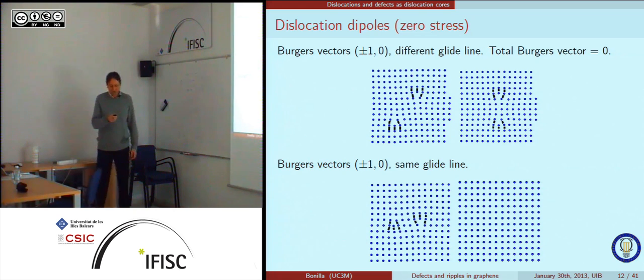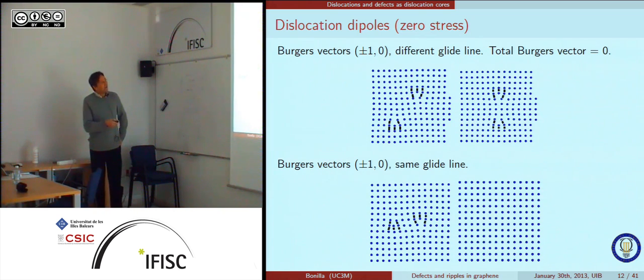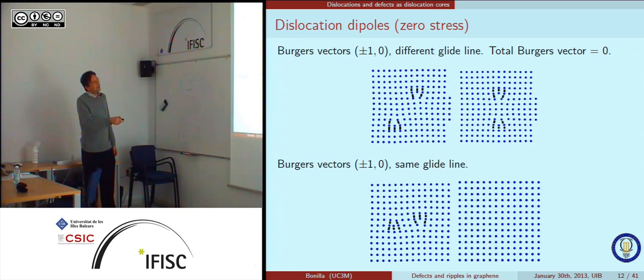Okay, so this is, for instance, what happens when you have several dislocations. And here we do not apply any external force. These two dislocations see each other and they exert a certain force. Since they have exactly the same Burgers vector along the x-axis, but this one points to the right and this one points to the left, they experience an attractive force between them. So in this case, you run the dynamics and you end up with this dipole there. Instead of having parallel lines, they share exactly the same line, while they attract each other, glide towards each other, and leave the lattice